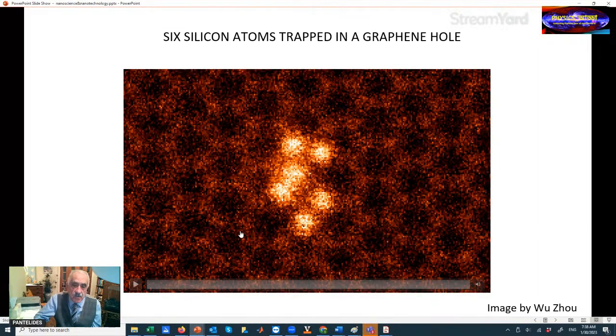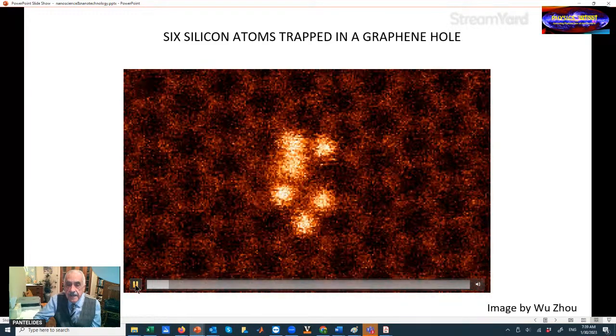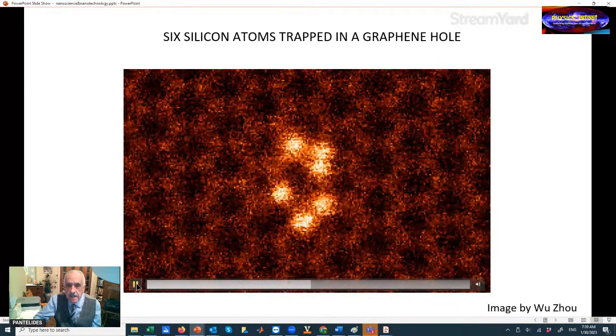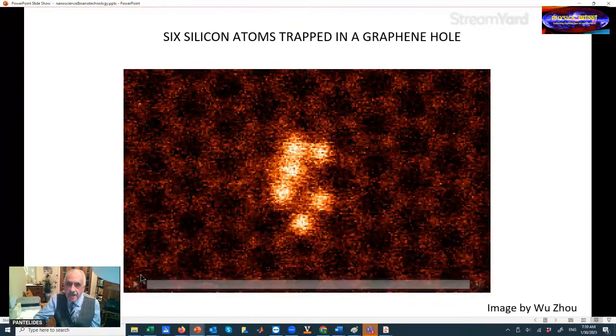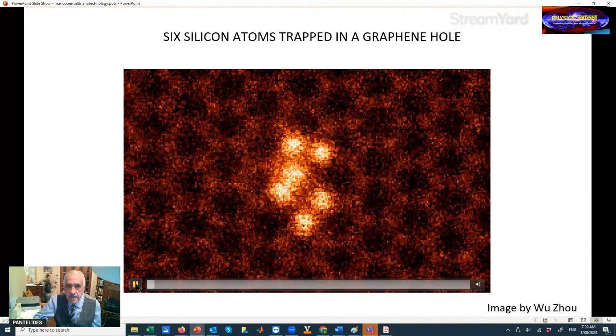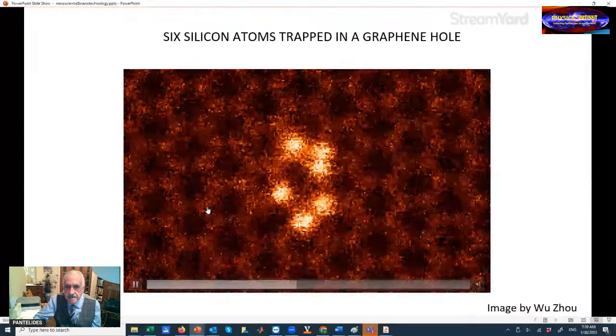Here is a case where my friend found a defect that had 6 atoms in it that were identified as silicon atoms. And they took so many pictures of them, they realized that one of the atoms was moving, and they made a movie out of it. And if you saw carefully, at one point it looked like there was half an atom over on the left and half an atom on the right. Watch it again. There.